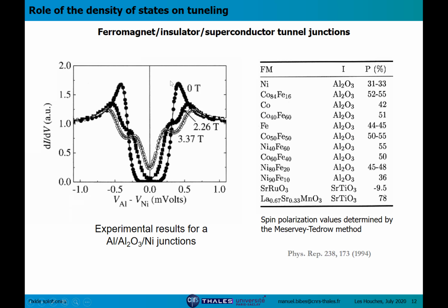At 0 field, we only see 2 peaks because there is no Zeeman splitting in the superconductor. And so the spin up and spin down currents are adding to each other, and they don't contribute different peaks. They are superimposed, if you wish. You can see also on the right-hand side of this table that the value of the spin polarization ranges between about 30 to 50, 55% with transition metals. Okay, so it's quite large. I mean that you have 2 spin up for 1 spin down, basically, in these kind of systems.